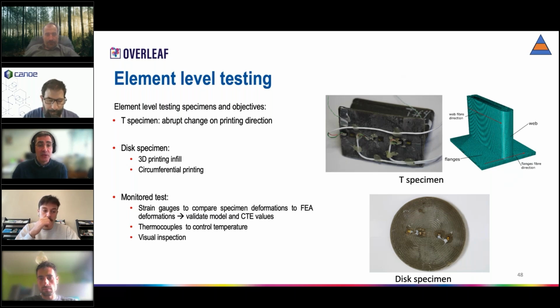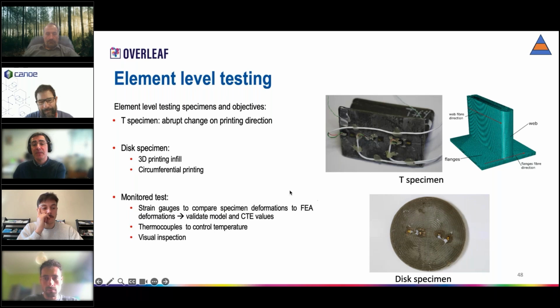So with Aymen Asiturri, we designed two different element level tests. One was a T specimen, this figure on the right top, that tried to simulate the change in the printing direction when you have a reinforcement. And we had another specimen, a disc specimen, whose objective was to simulate a 3D printing infill or circumferential printing. All these specimens were instrumented with strain gauges and thermocouples and put at 20 K and at different thermal conditions to see the damage and to get the response of these materials, to see if there was failure or there wasn't.